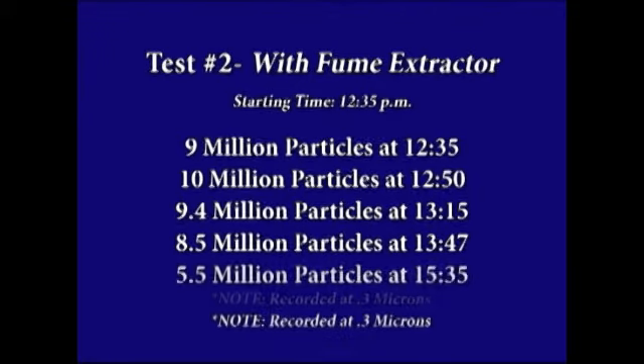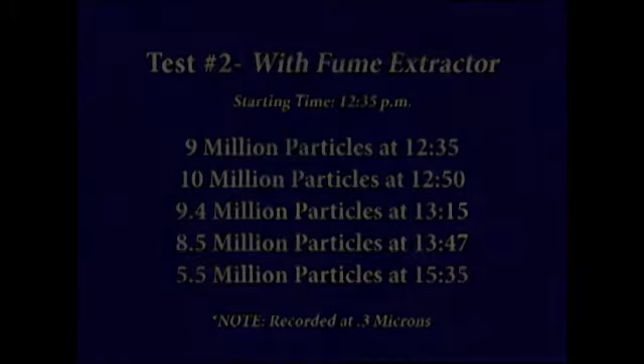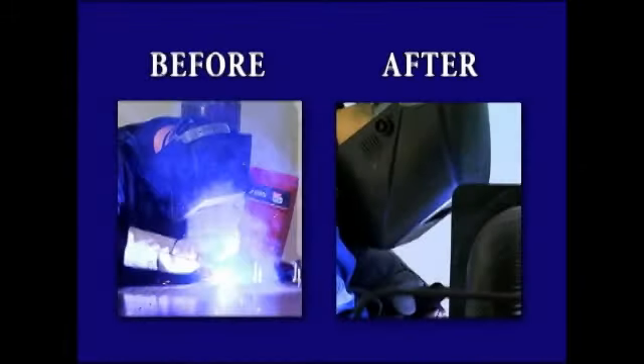Approximately 3 hours later, the welding fume extractor had achieved a particle count of 5.5 million, which was even lower than the morning count prior to welding commencement. As the before and after picture illustrates, you can clearly see that the welder was smothered with smoke while welding without the Sentry Air Systems welding fume extractor.